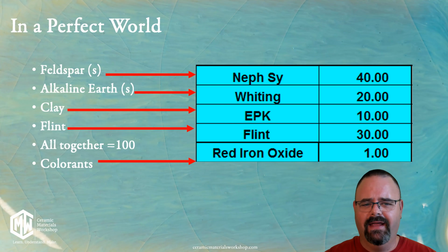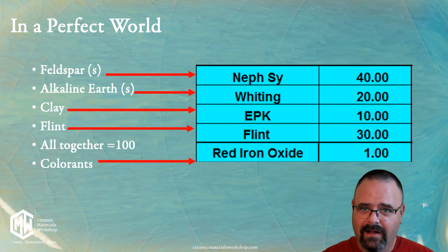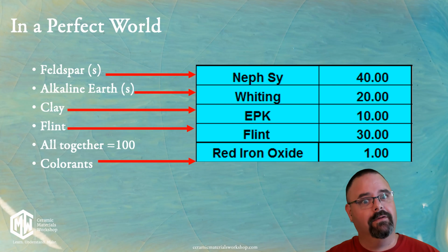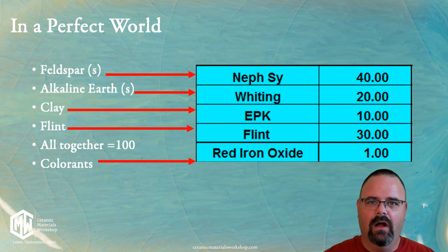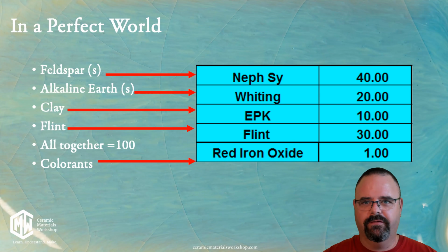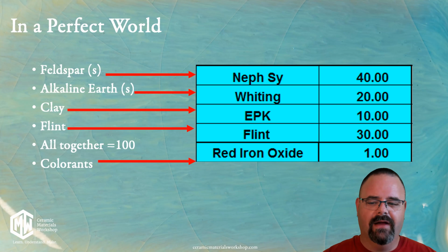This is a very common glaze formula for a basic cone 10 glaze called 4-3-2-1. It's 4 ingredients. When you add them all up together, they equal 100 plus the colorant. It's technically 101, which is another topic for another day. But in this case, they equal 100. Those are the nepheline syenite, which represents our feldspar, the whiting, also known as calcium carbonate, which represents our alkaline earth flux. We've got clay, kaolin, we've got flint, silica, and all of those together add up to equal 100, and then our colorants go on top of them. You weigh out your materials, you mix them together, and then that's your glaze. That's about it. But what we really want to talk about is the application.